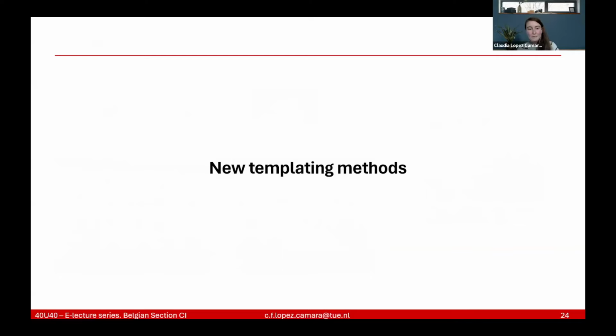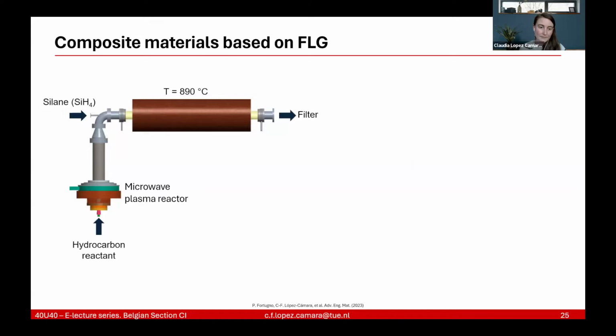So with that said, we moved to another topic, but it's still using the templating and the plasma reactions, the plasma gas phase synthesis. And that was also kind of unexpected. We started with the plasma reactor, pretty similar to before, with a reactant coming from the bottom. We wanted to create composite materials with few-layer graphene, so we were putting in ethanol, a hydrocarbon reactant, in the microwave plasma reactor, and then we were putting in silane from the side as a secondary precursor in order to get some sort of mixture between few-layer graphene and silicon. We were passing it through this high temperature hot wall at 890 degrees Celsius, and then collecting it in the filter, and it was looking like this.